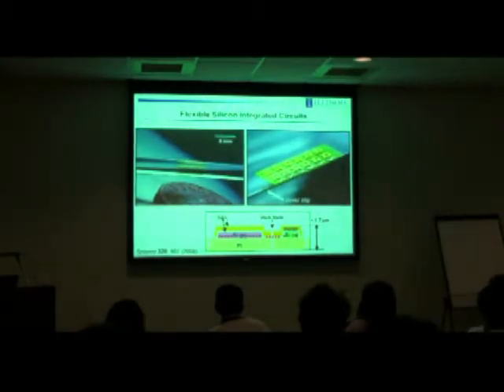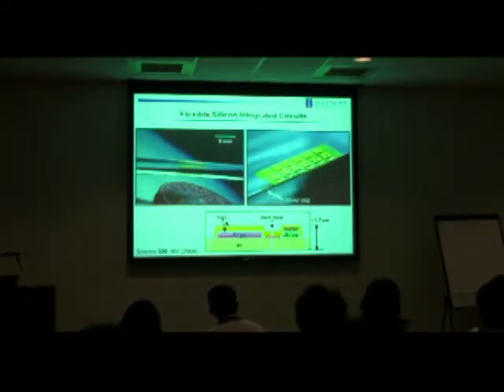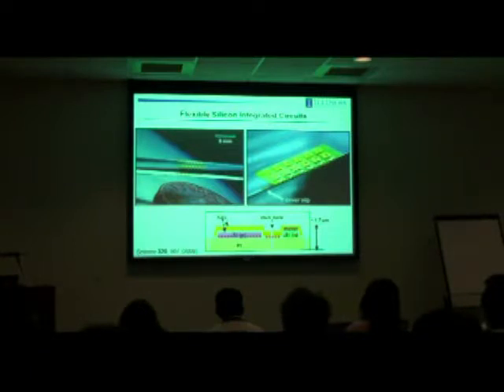If you take that form of silicon, there are different ways to manipulate it and integrate it onto a thin, flexible substrate to make a flexible but still high-performance form of electronics, as an alternative to this organic approach that we worked on and others are still working on over the years. This is an example of an extreme implementation of that particular idea in the form of simple silicon CMOS circuit elements. What this consists of are very thin ribbons of P and N-type silicon, and then other layers of material to form simple logic gates. These are CMOS inverters, an array of them. And they're built on a very, very thin sheet of plastic. This is polyimide, just to illustrate how bendable you can make a silicon circuit. In this case, making the silicon thin and also making the substrate thin makes this very bendable by virtue of the mechanics I just described.